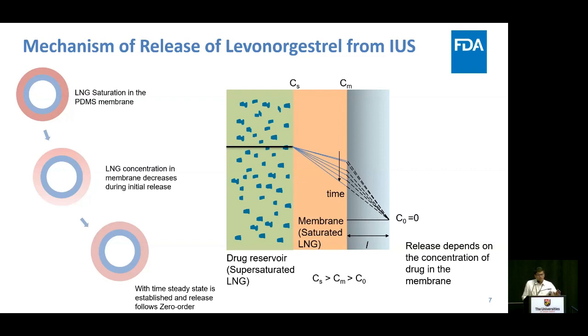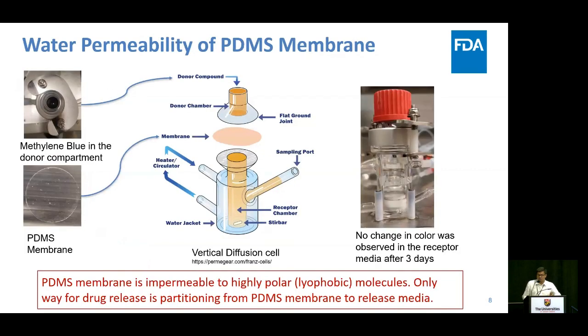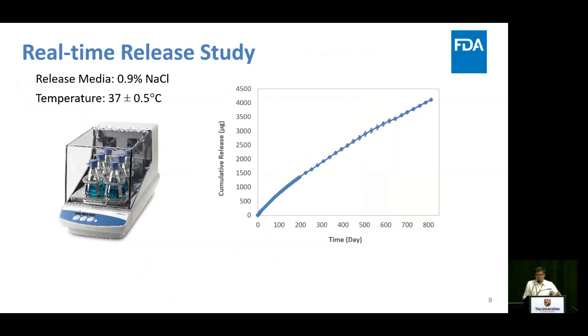Once we had this hypothesis, next we checked the permeability of the PDMS membrane in water. We found that the PDMS membrane is impermeable to water or aqueous solvents. So this gives us very important information: the drug release from these devices is dependent on drug partitioning, not on solvent-mediated diffusion. Then we developed real-time in vitro release studies in normal saline at 37 degrees Celsius. We're still continuing this study. It is more than 800 days now, and we'll continue for 3 years or maybe a little more.